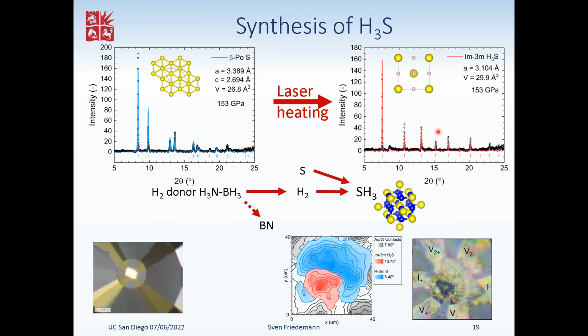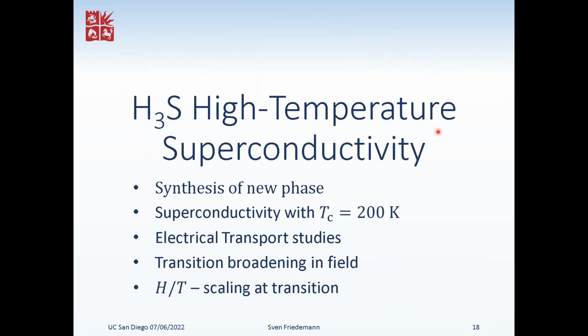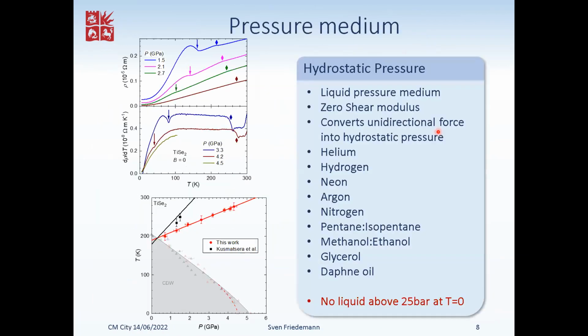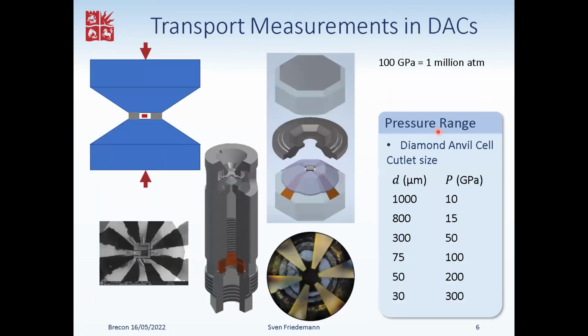The second question was about the orientation dependence of the magnetic field. We're limited to one orientation because our pressure cells are long cylinders, as I've shown here, specifically made such that they fit into the magnetic field with the field along the axis of the cylinder. In smaller fields we could potentially rotate a little bit, but not by more than 10, 15 degrees. But we've not yet done this.